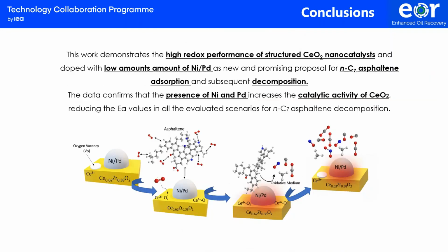The data also confirms that the presence of nickel and palladium increases the catalytic activity of ceria, reducing the activation energy values in the evaluated scenarios for asphaltene decomposition at different pressures and different temperatures, due to the strong metal-support interactions.